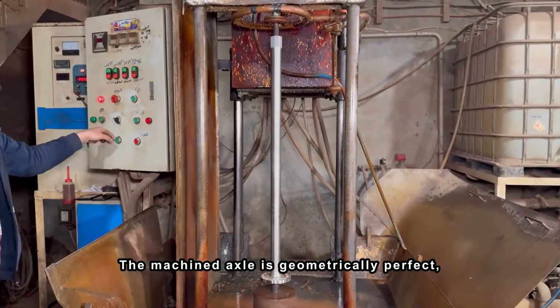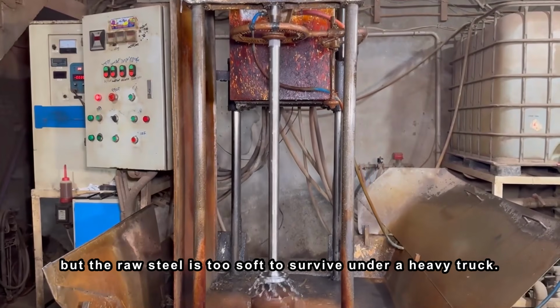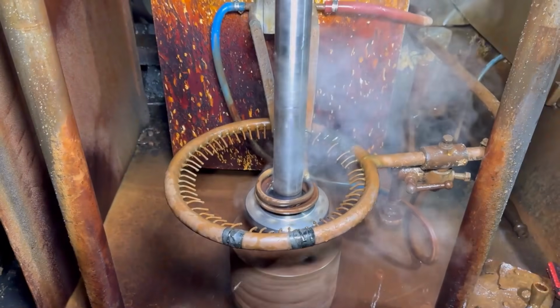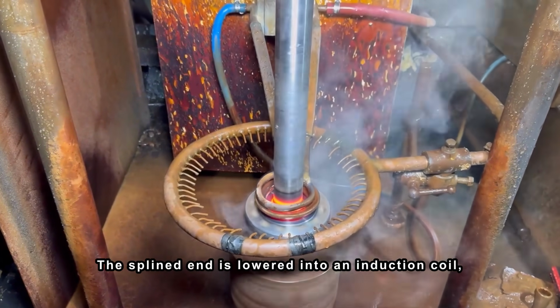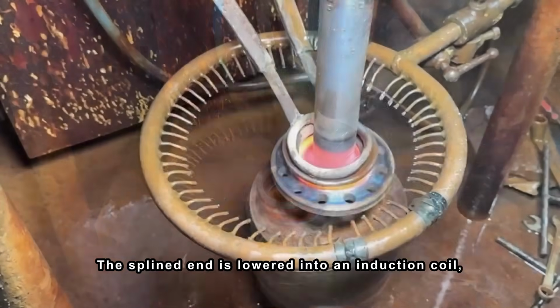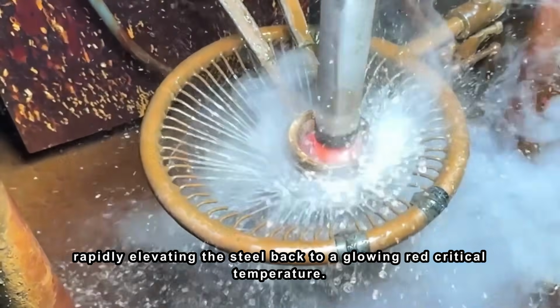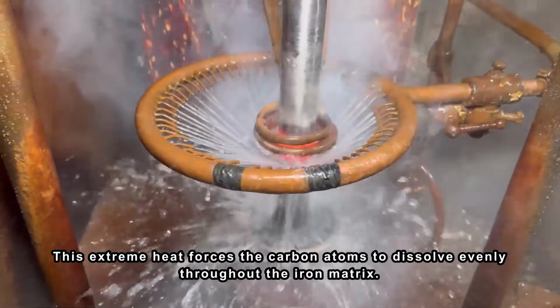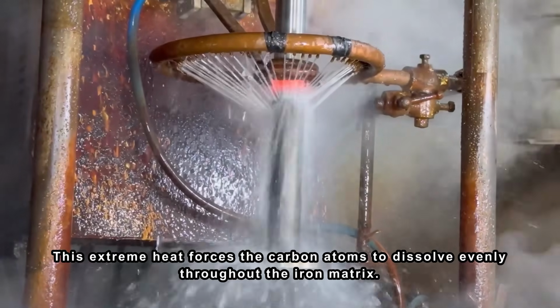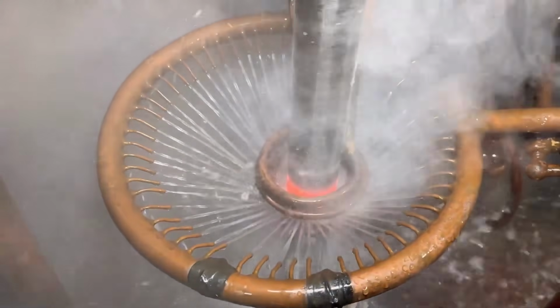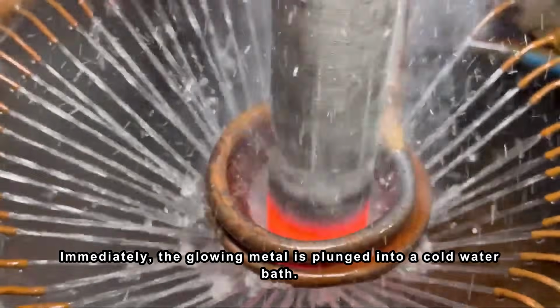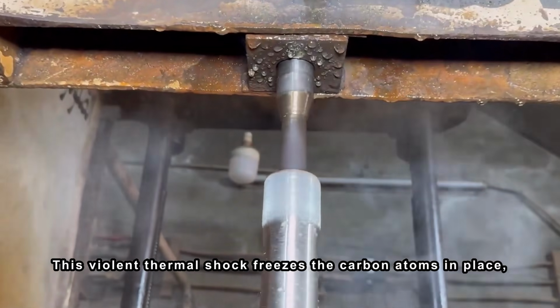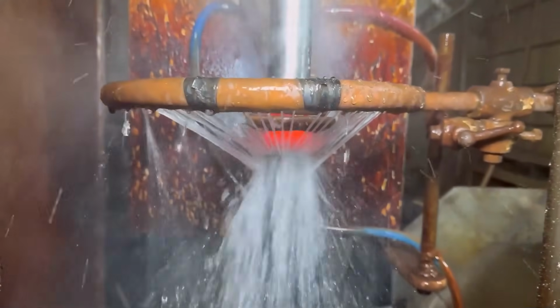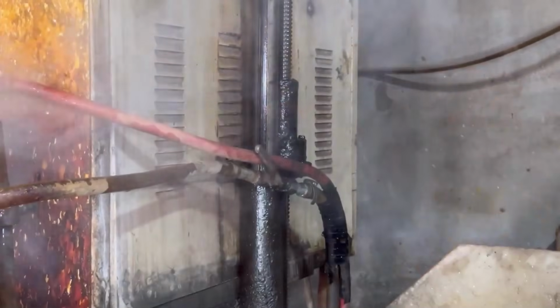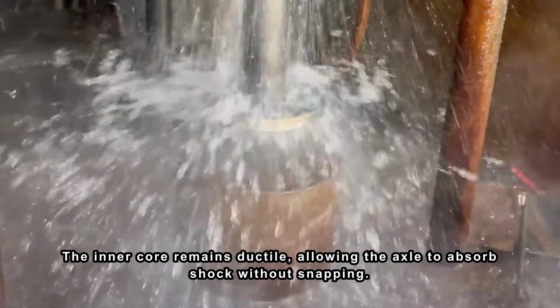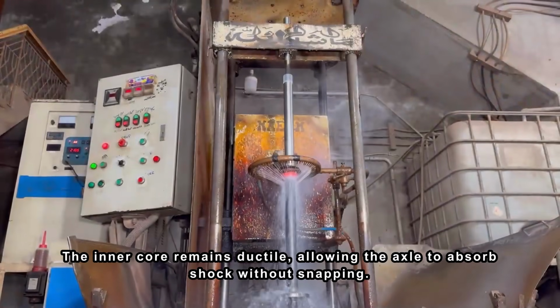The machined axle is geometrically perfect, but the raw steel is too soft to survive under a heavy truck. The final step is aggressive heat treatment. The splined end is lowered into an induction coil, rapidly elevating the steel back to a glowing red critical temperature. This extreme heat forces the carbon atoms to dissolve evenly throughout the iron matrix. Immediately, the glowing metal is plunged into a cold water bath. This violent thermal shock freezes the carbon atoms in place, creating an incredibly hard, wear-resistant outer shell. The inner core remains ductile, allowing the axle to absorb shock without snapping.